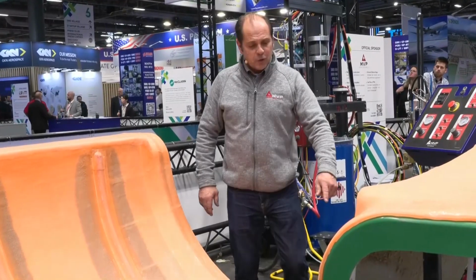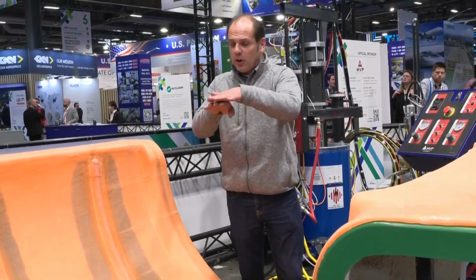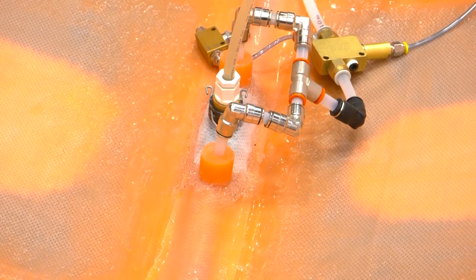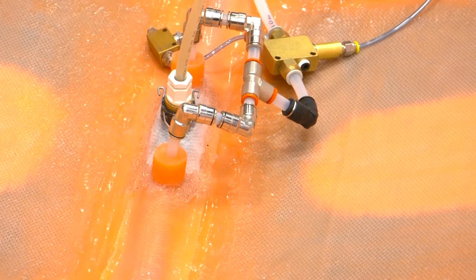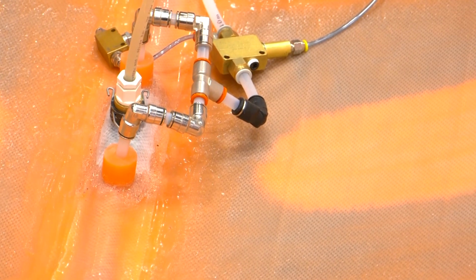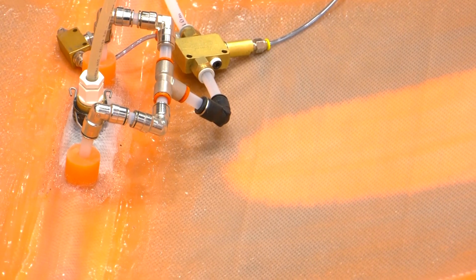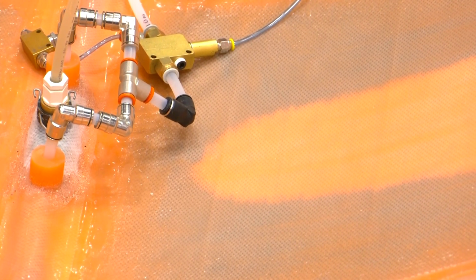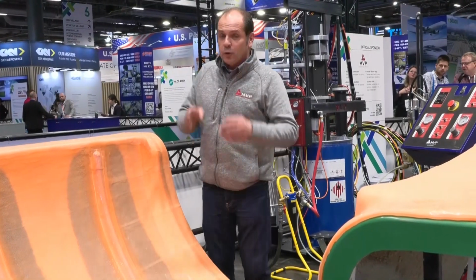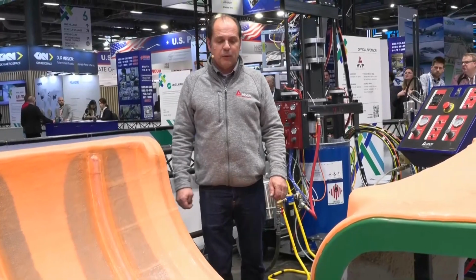So the little lines that you see here are the carbon overlaps that we have made. So of course we have a little bit more, so it's a little bit longer. So now we pull the vacuum all around the part, so the resin stops here. The resin will fill here. What I have done also, I stop the groove 2 centimeters before the end of the part to equilibrate the end of the resin flow.